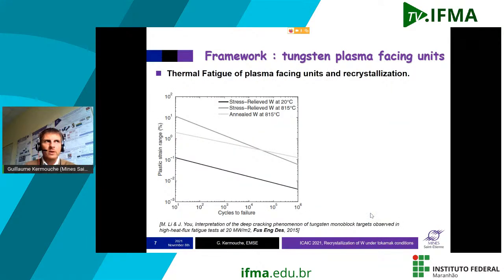So why does recrystallization drive the crack? We will see that from the thermal fatigue curve. So just to understand this kind of curve, here you have on this axis the plastic strain that happens during a cycle, and here the number of cycles to failure. So if we consider the black curve here, this is the fatigue curve for the material at room temperature. If you have a plastic strain of about 10^-1, the number of cycles to failure will be 10, something like that. If it is 10^-2, so 10 times lower, this will be 10^4 cycles to failure. Okay.